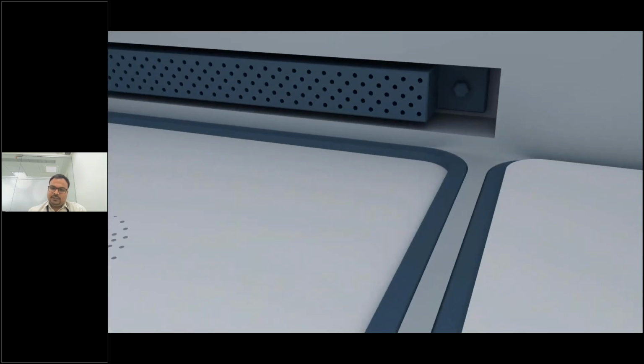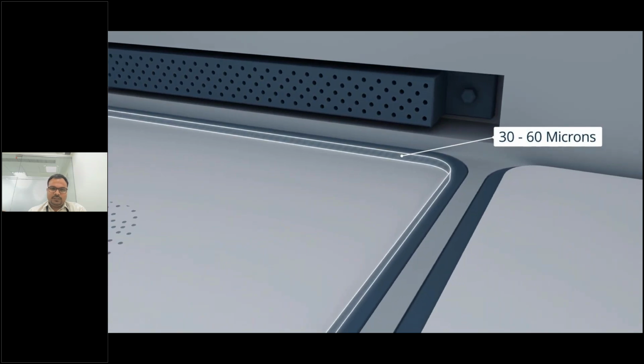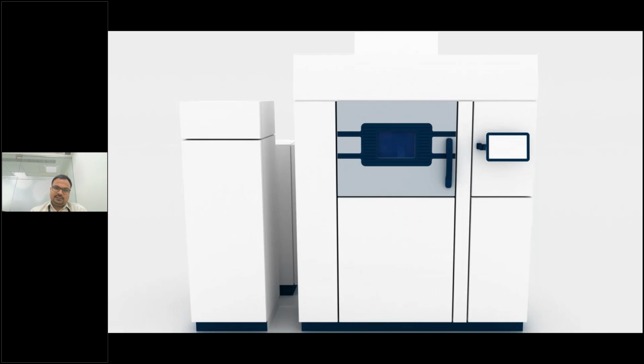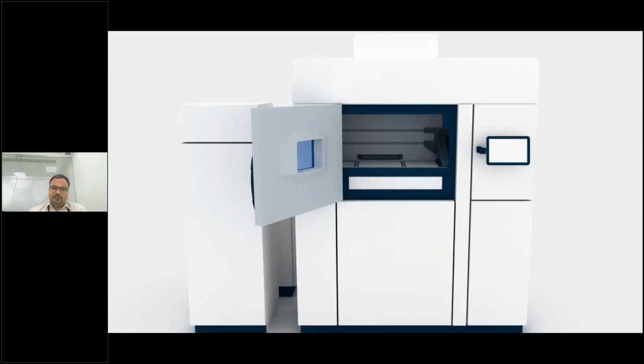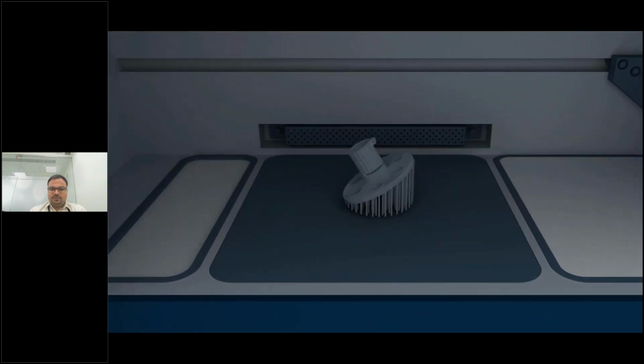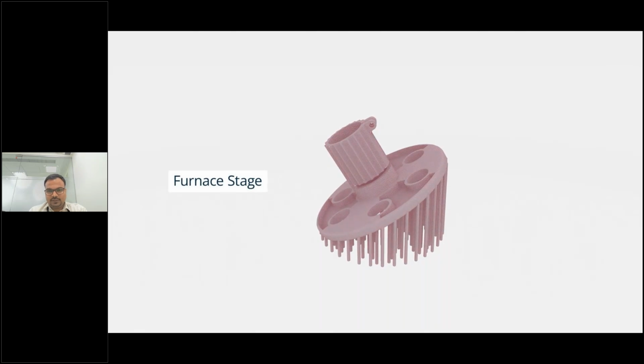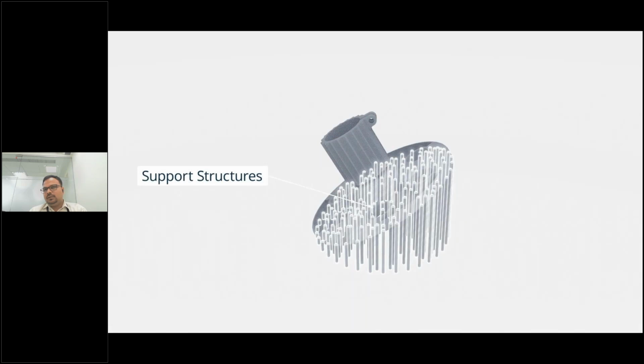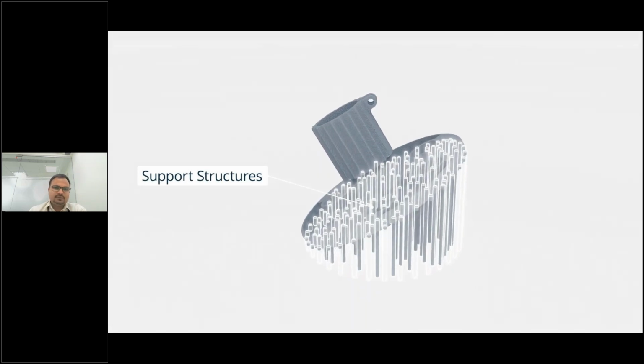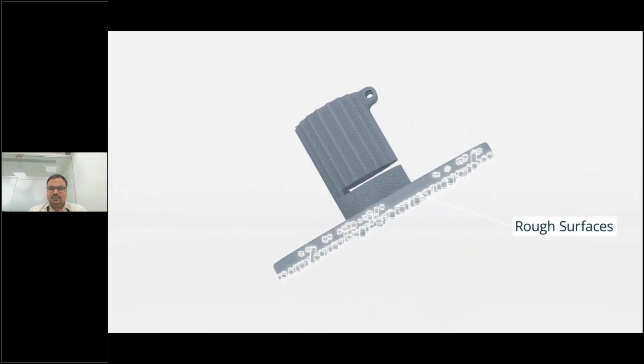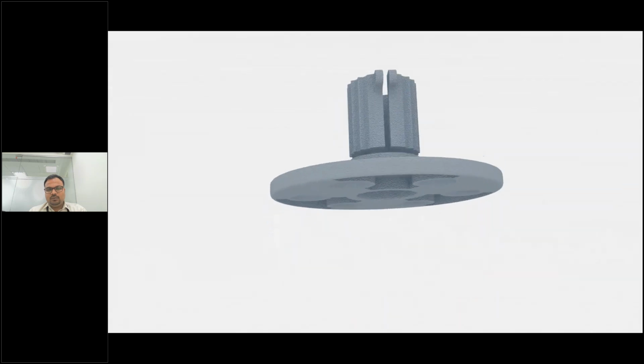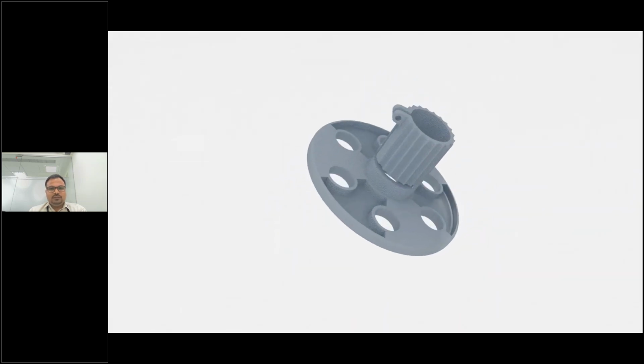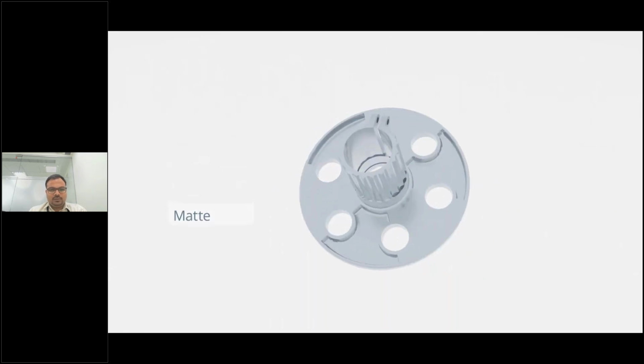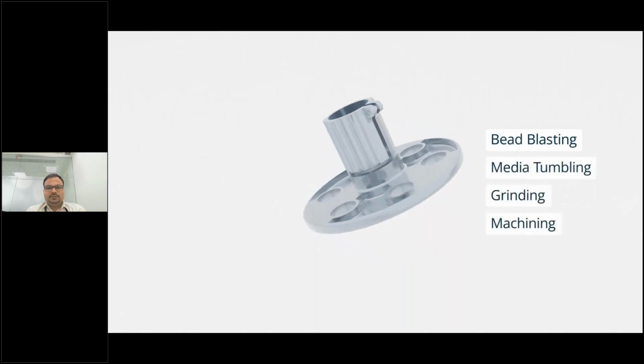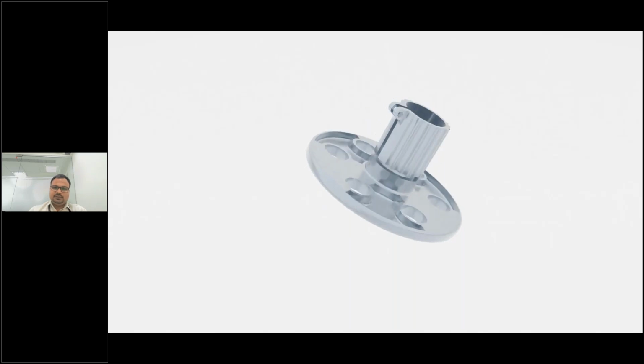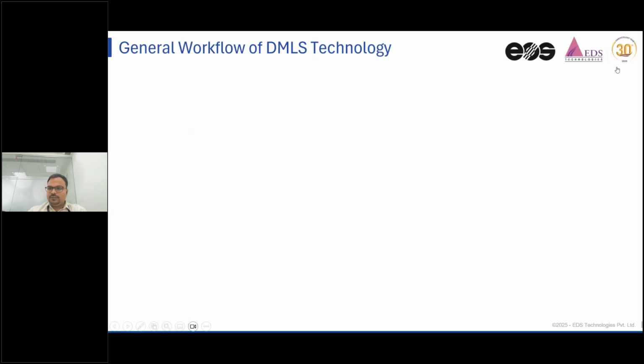It recoats the powder in a layer thickness starting from 20 micron to 60 micron or 90 micron, depending on the requirement. Once the coating is done, the laser addresses those 2D layer information, and once the printing is over, again we depowder and take out the part, put it in a furnace for stress relieving, and remove the support structures. The DMLS process comes with support structures, of course, and those need to be removed after the stress relieving process. After that, we can choose what amount of post processing we need to do on the part, whether machining, EDM, wire cut, or polishing. All of these processes are supported by our 3D printed materials. So this is how the DMLS process works, from powder form to the final component.